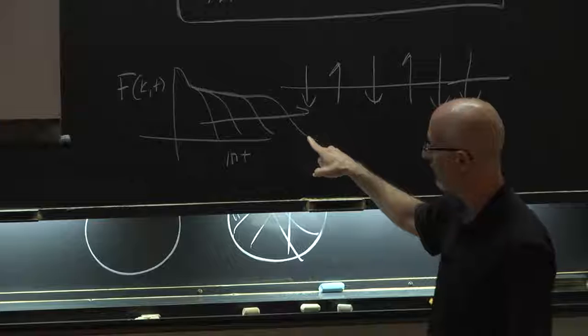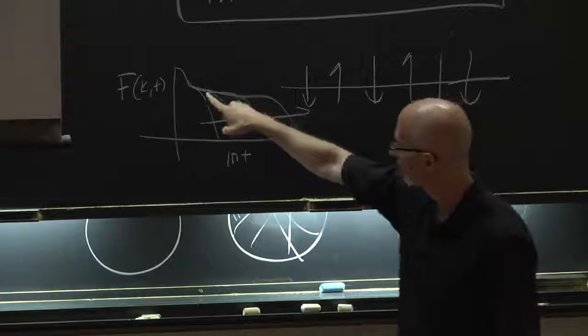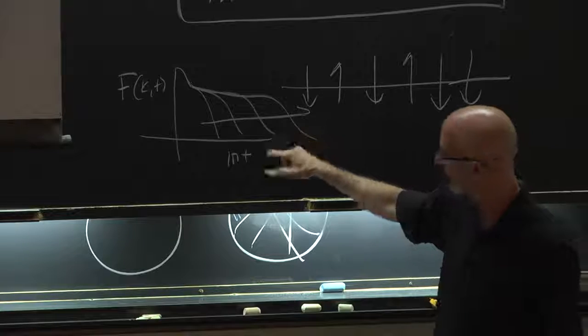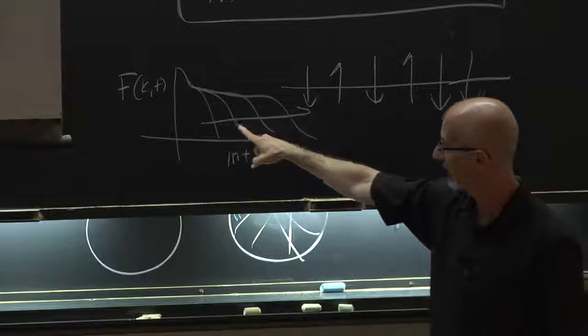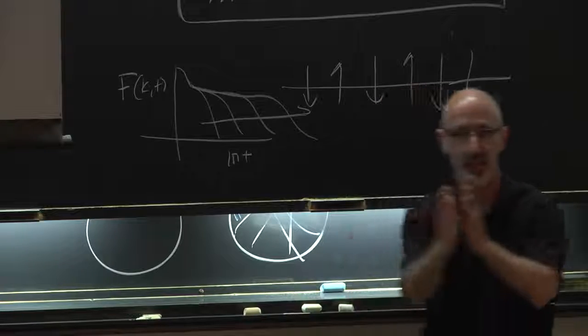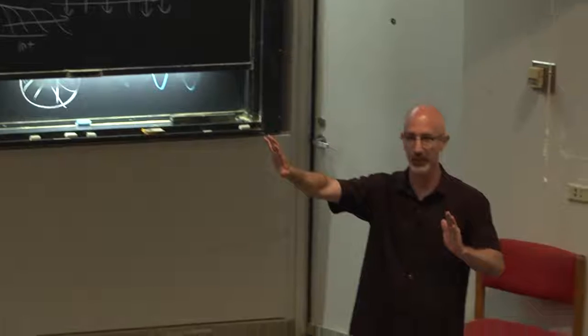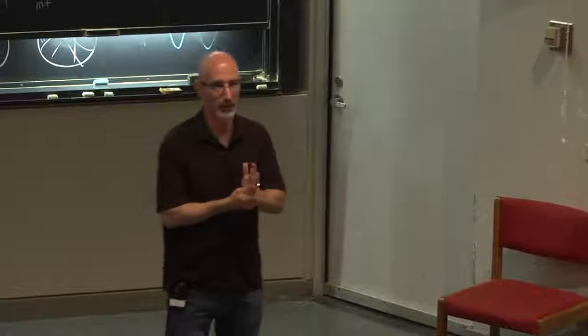You see this multi-time scale behavior with the plateau and some stretched exponential relaxation, and a relaxation time that's getting much, much larger as you cool the system down. But what you find is that the higher the dimension you go to, the further away you can push the hopping-like motion that we started this discussion with. And together with that, the Stokes-Einstein violation basically goes away.